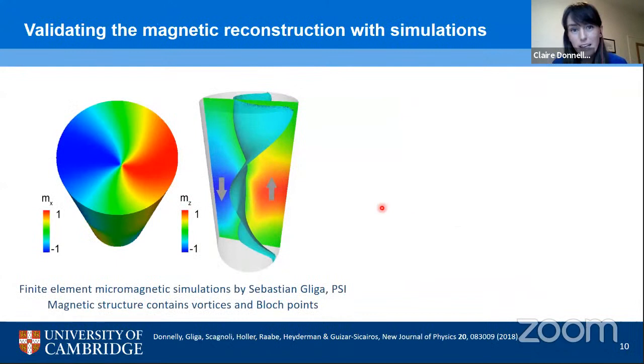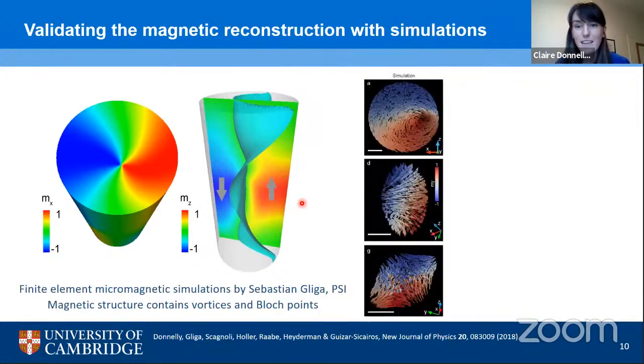So we performed simulations of our magnetic tomography process, specifically using a micromagnetic simulation that was calculated by Sebastian Gliga at the Paul Scherrer Institute. This micromagnetic simulation was particularly useful because it contained a number of very similar structures to what we observed in our experiments. We saw vortices, Bloch points, and anti-Bloch points.